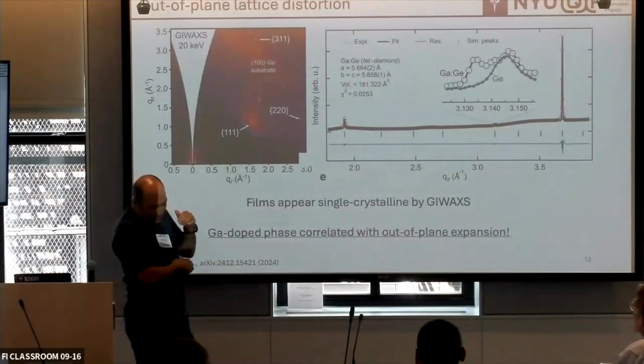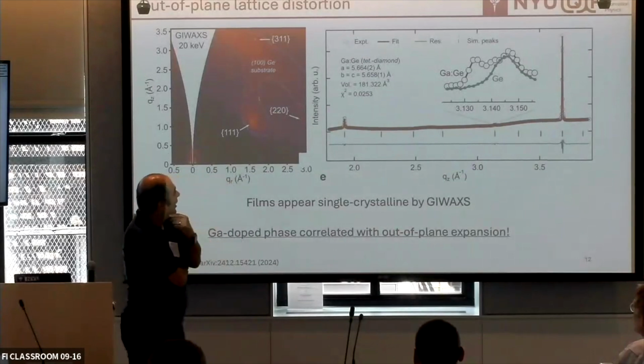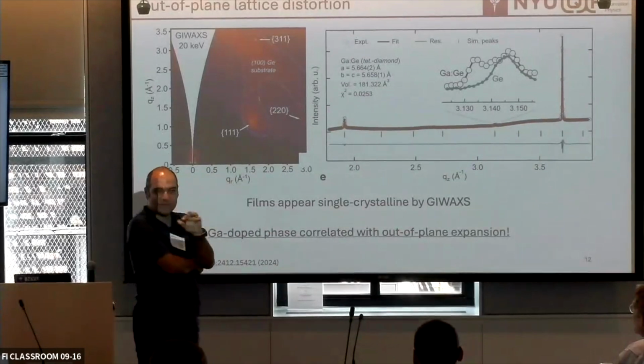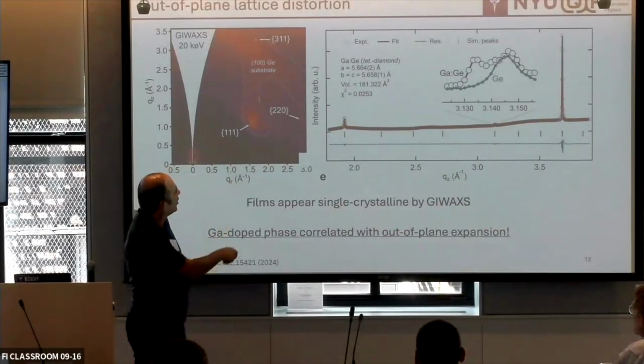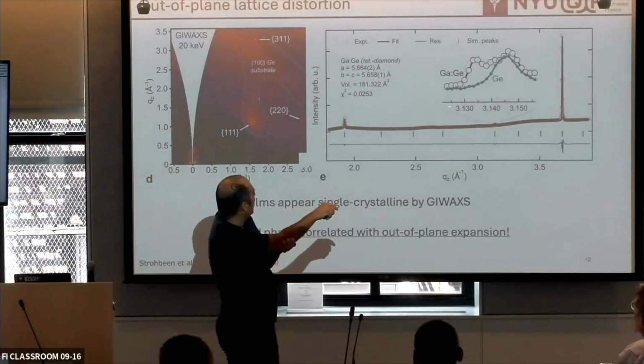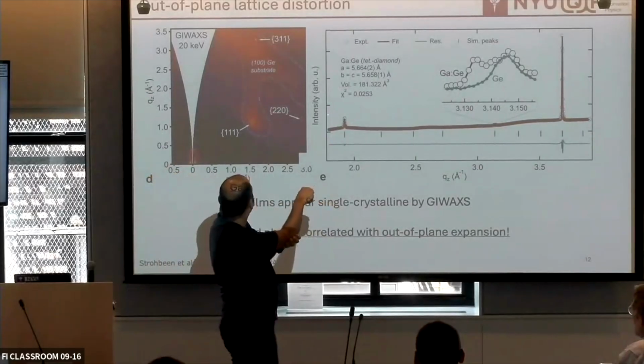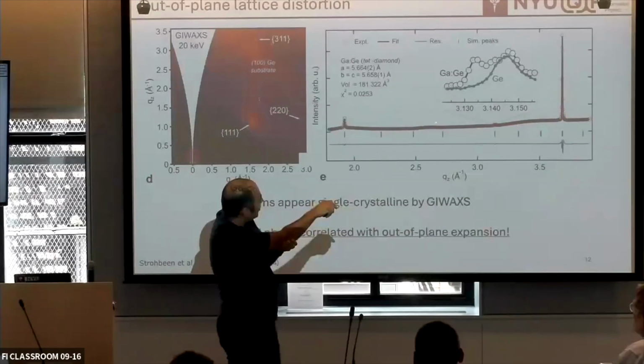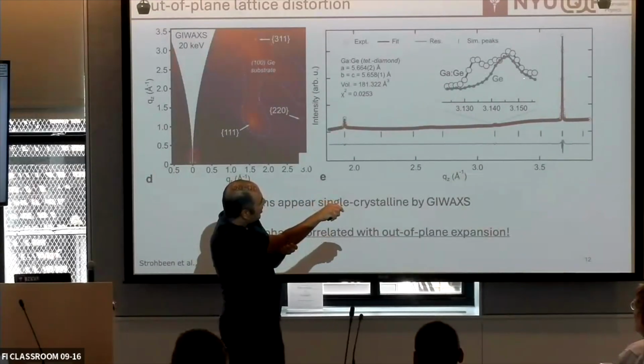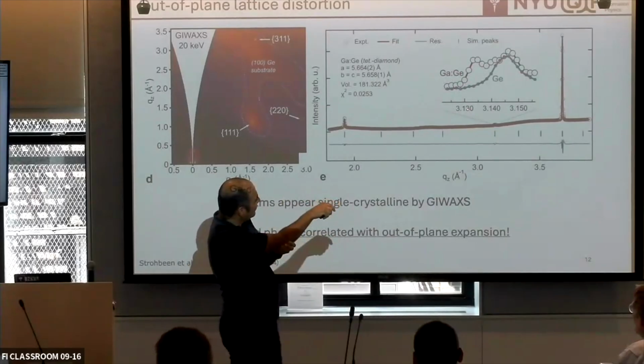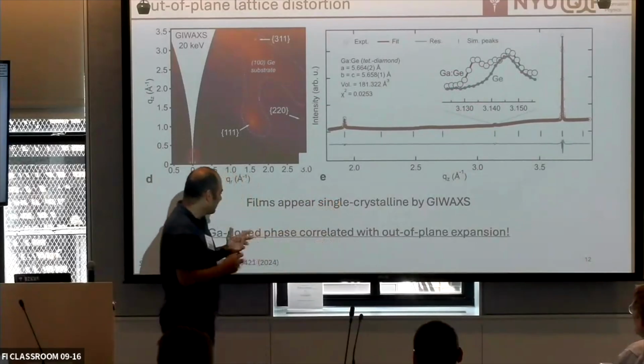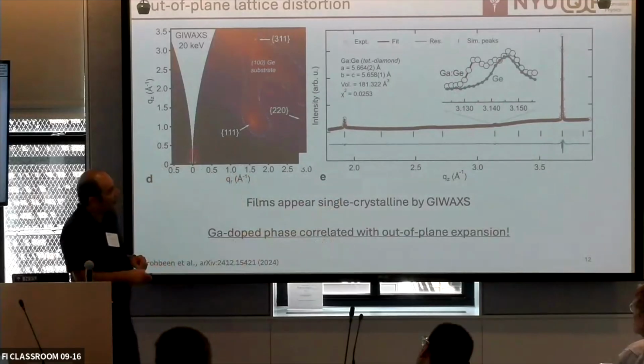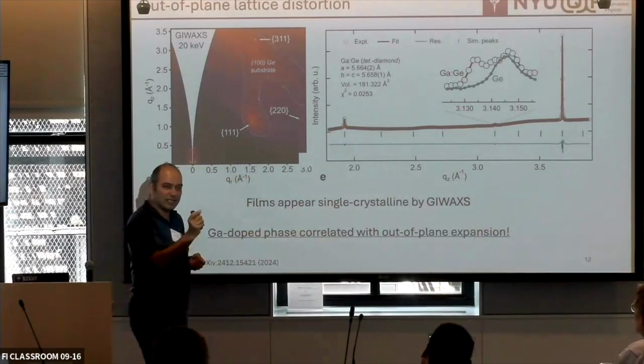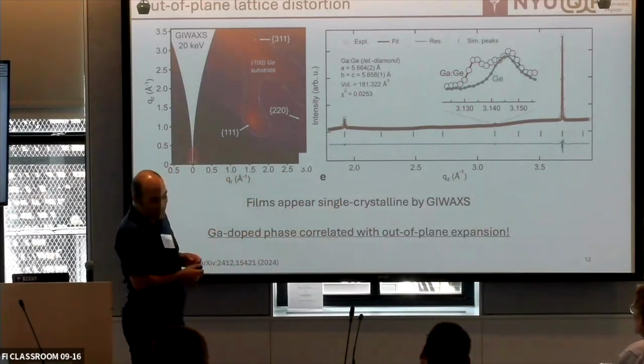We then started thinking about this maybe from a Raman-type experiment. Can we get any insight from electron-phonon coupling? So we put a germanium substrate, and then we look at this, and you see that there is a peak for germanium here, and then when you dope it, there's a small distortion, but it's not a massive number. So at least, this is consistent, as I will show you later with DFT, with just the substitution.